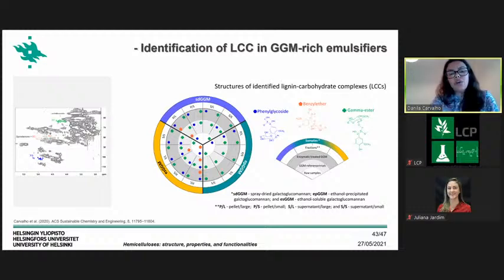And we could also check that using physical fractionation, based only on the centrifugal forces or filtration, we could improve the identification of benzyl ether in the sample. And we also proved that the simple chemical fractionation using an anti-solvent strategy is efficient to concentrate some LCC bonds in the sample. In this case, it was also the case of the benzyl ether. This NMR spectra that you can see here just shows the position of the cross signals where we are expecting to have the LCC bonds, proving that our GGM sample was functionalized.